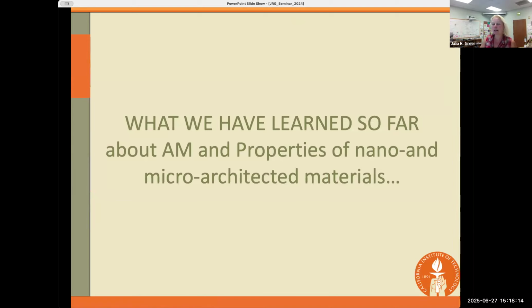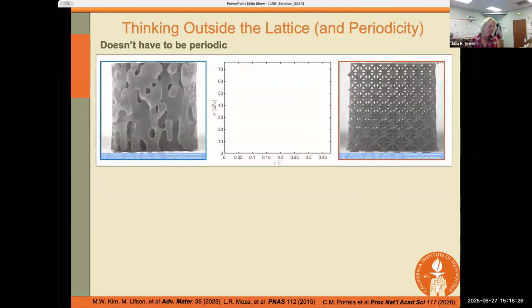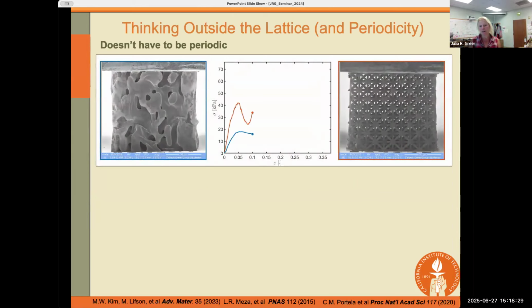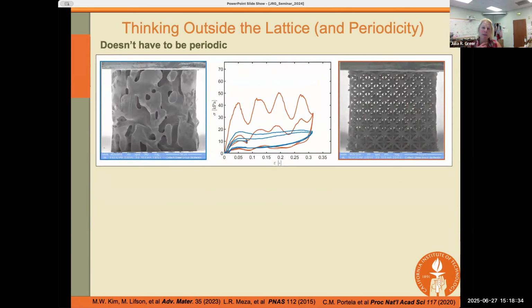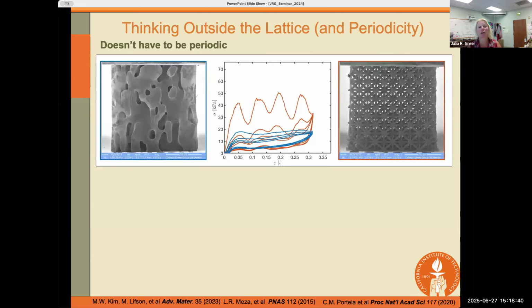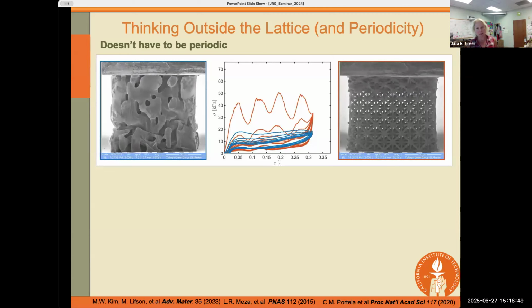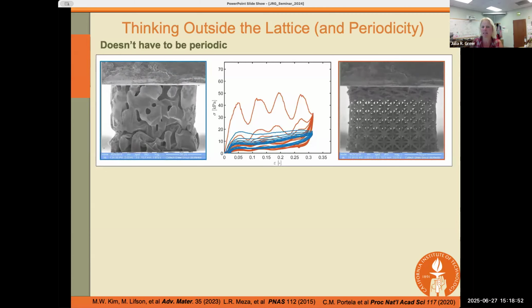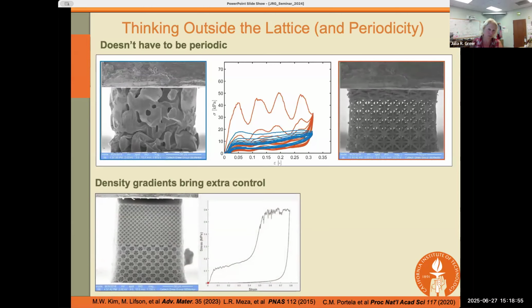So this was the introduction to basically bring all of you into our world, where we're very interested in the nano-induced size effects in materials and how they can manifest themselves at the larger scales. We've learned a lot since that point. One example I'm showing here is that this recoverability of brittle nano-architected materials spans beyond the periodic architectures. On the left-hand side, it may look like trabecular bone to you. So this is not beam-based. This is entirely shell-based, entirely curved surface-based material, all made of alumina. And you can see that this recoverability prevails over many, many cycles without any visible damage to the structure.